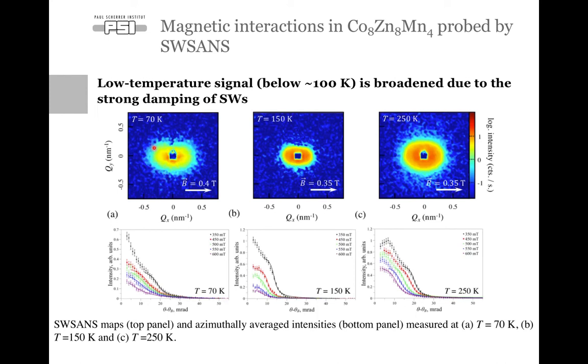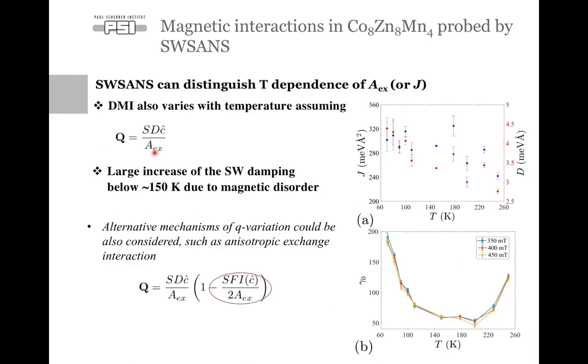the cutoff of this spin wave scattering intensity and the width of this scattering peak, from which we actually deduce the spin wave stiffness eventually. However, we could reliably obtain the exchange parameter from this data. Here it's shown in blue, and we again see the increase of the exchange parameter from room temperature towards low temperatures.